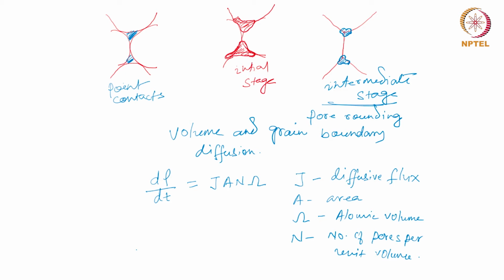will be eliminated more rapidly compared to isolated pores, because along the grain boundaries, first of all, the diffusion is happening, and we have also seen before that the grain boundary diffusion is actually faster than volume or lattice diffusion, and therefore if you have pores like this which are along the grain boundaries, so the diffusion which happens along the boundaries will actually result in the filling of these pores first, compared to isolated pores which may be located somewhere else in the lattice.